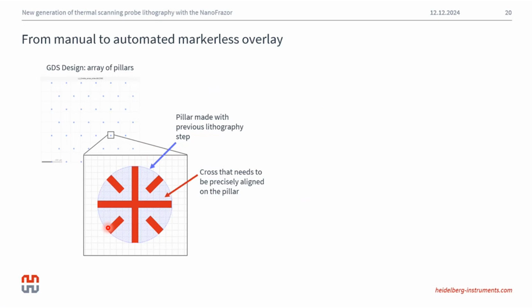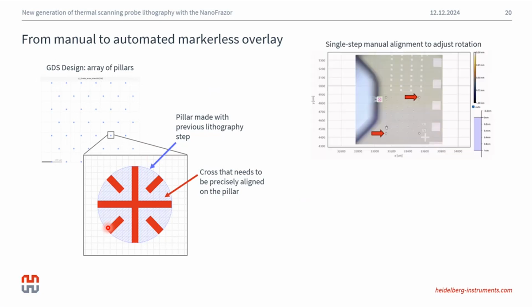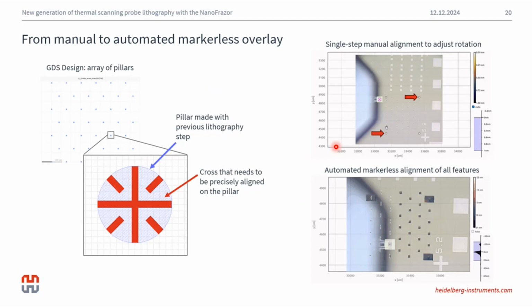The way we would do so is as follows. We would need to do a manual alignment only in the beginning, and that is to the two opposite extremities of the nanowire array. And the way we do that is by scanning over these nanopillars at opposite ends of the array, and we do so to adjust the rotation on top of these nanopillars.